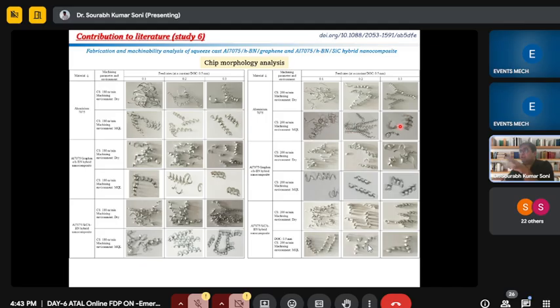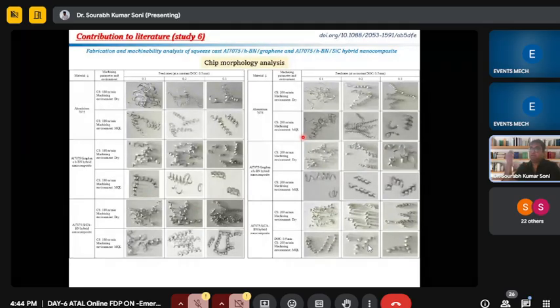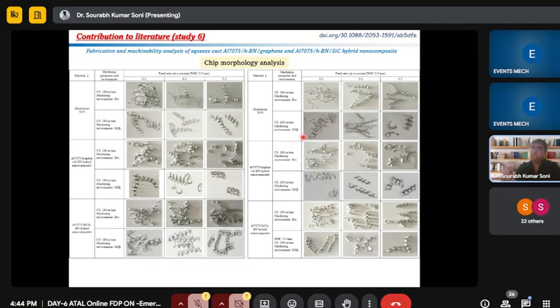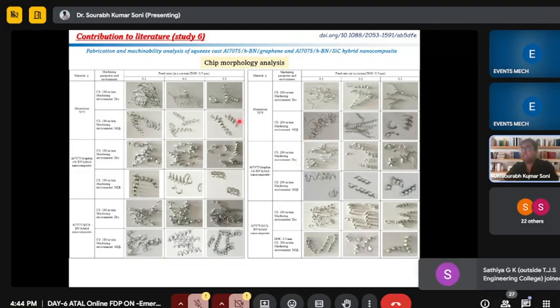From this image, we can analyze that the self-lubricating hybrid nanocomposite, because of adding HBN and graphene, is showing low surface roughness as compared to the conventional composite. So we can use this composite in components which will be subjected to machining operation. Because composite preparation is one thing, application is another thing. For application, we must surface finish our specimen, either by milling or turning. Within turning or milling, we must analyze how our specimen behaves.